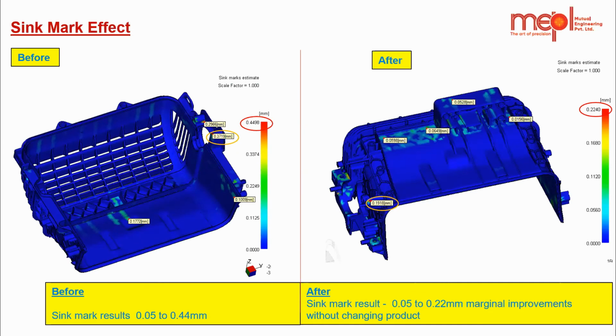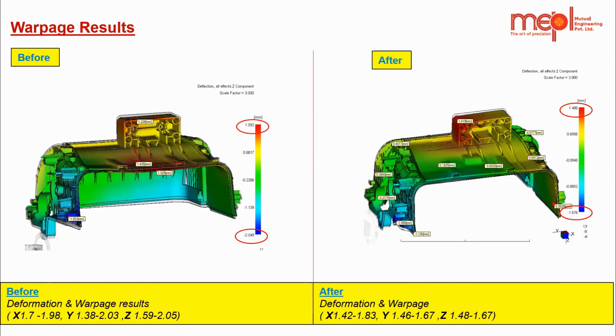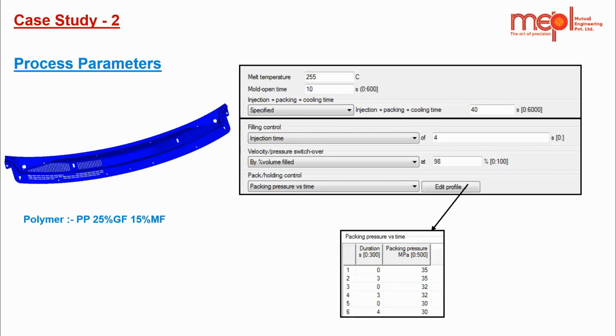You can see that after changing the cooling lines and reducing the mold cavity temperature, the sink mark observed earlier was 0.05 to 0.44, which reduced to 0.05 to 0.22. So cooling has actually given better results, which we can see through the simulation. It also gave a good result in warpage and deformation. Before it was a little bit high, and after that it reduced to some extent. So this is our case study number two.